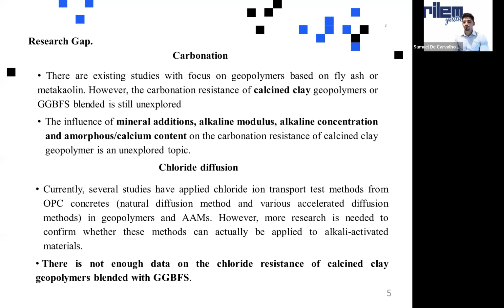Also the chloride diffusion of this composite. A lot of studies have applied chloride transport test methods from OPC, in a natural diffusion method and also an accelerated diffusion method. In this specific project, we are using these results to build a big database from our research group, to confirm if these methods that were developed for OPC can be replicated on alkali-activated materials. Also, we don't have enough data on the chloride resistance of calcined clay geopolymer blended with GGBFS.